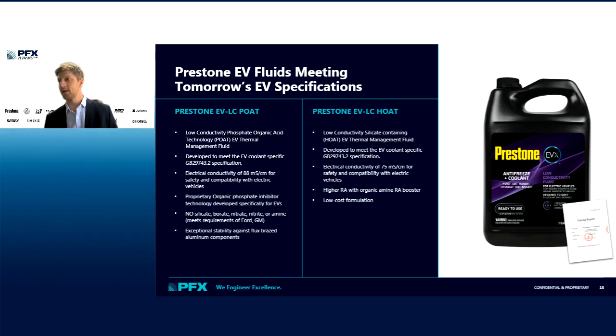The second option is the HOAT type product. Now, this is a silicated product, still meets the GB 29743.2 specification. Low electrical conductivity, 75 microsiemens. And the benefit here is this has a higher RA due to an organic RA boosting additive within the formulation. So 2 different flavors of GB compliant formulations are ready out of Prestone EVX.